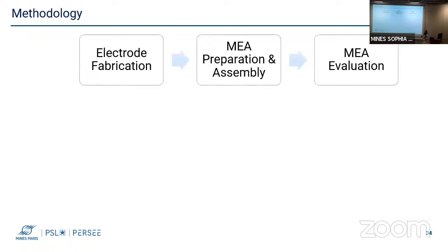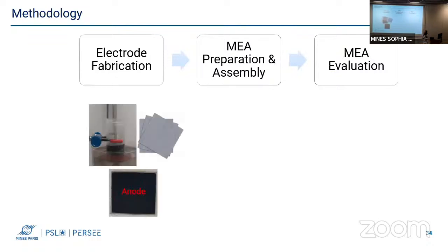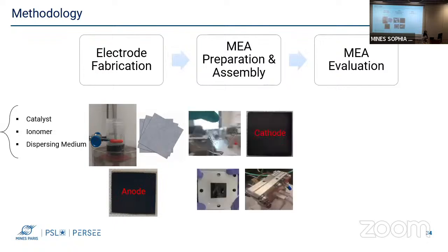The evaluation of different materials starts from the electrode fabrication, which consists of spraying a catalyst ink on a porous transport layer. The composition of this ink, which consists of the catalyst, the ionomer, and the dispersing medium, has a great impact on the final performance of the MEA. For this reason, we decided to prepare and evaluate different ink compositions, specifically working on the catalyst and the ionomer. After that, the MEA should be prepared by treating the membrane and assembling the cell.